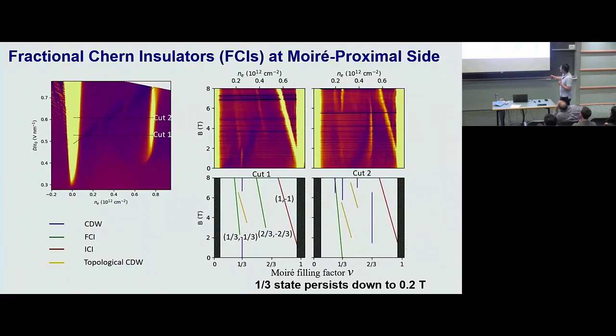When you apply a magnetic field, okay, and you do line cuts at position 1 and position 2, you actually can induce a state that has a fractional slope, these green lines indicated here. So it could be that at 0 magnetic field, CDW is the true ground state, the most stable. But when you apply a magnetic field, you can observe a transition from CDW to FCI, and this is a fractional Chern insulator state with slope of -1/3. There's also a state with slope -2/3 stemming from filling factor 2/3. But there's also a Chern insulator state, integer 1, with slope -1 stemming from filling factor 1.